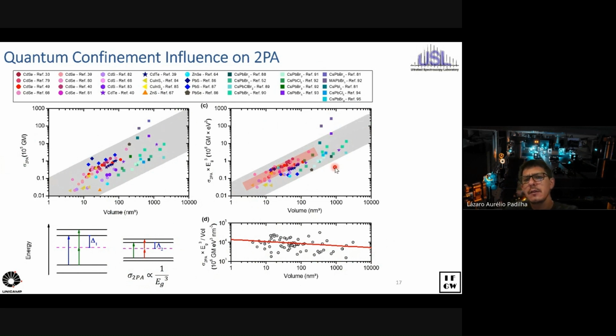And honestly, my guess here is that the dispersion for cadmium selenide is much narrower than for perovskites just because cadmium selenide has been studied for a much longer time. So the mistakes people needed to make to learn the right way to study this in cadmium selenide have been made in the past. And now people know what to do and what not to do. The same is not true for perovskite quantum dots, which were created just a few years ago. And so I expect that in the next few years, most of these results will come down to a much narrower distribution than the 2 orders of magnitude shown here.